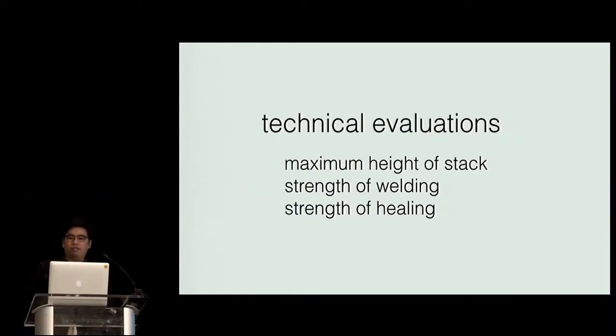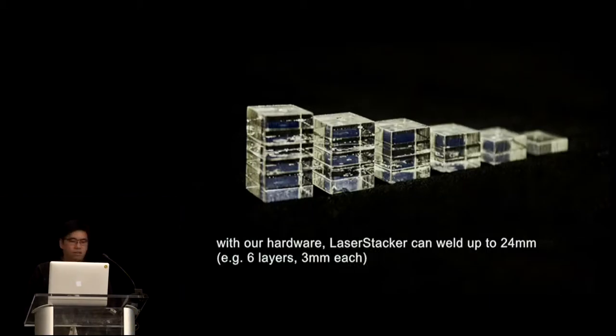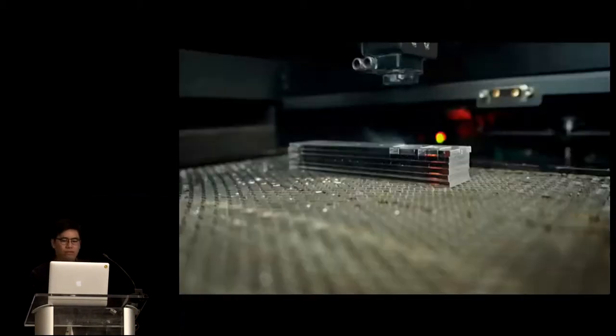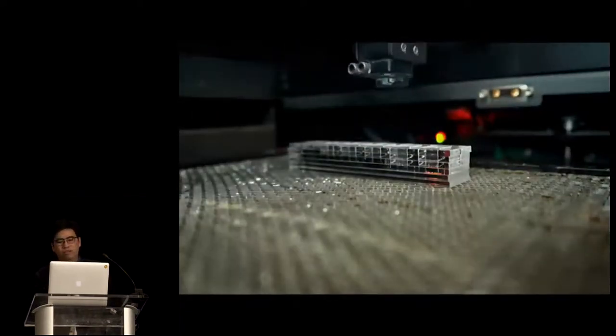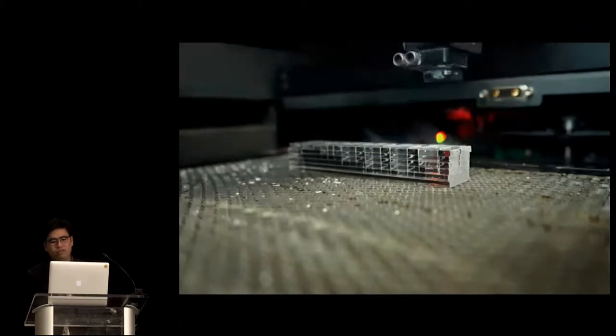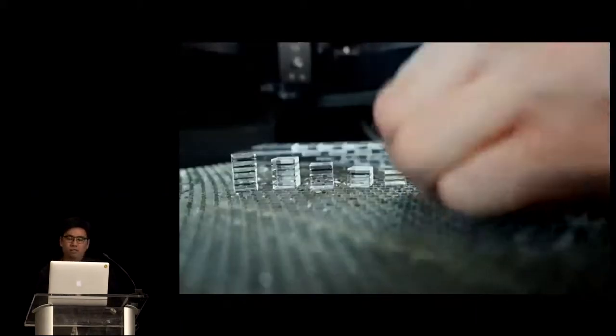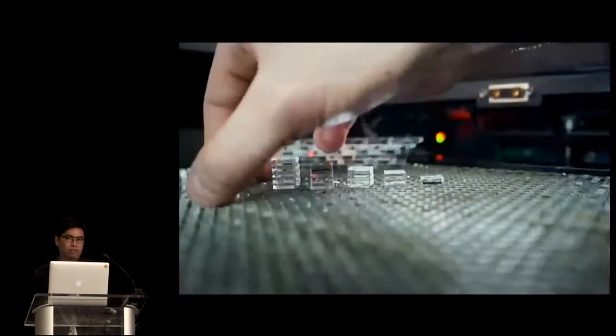All right. Finally. So, we also did some simple technical evaluation. To evaluate the maximum height of stack, strength of welding, and strength of healing. With our hardware, laser stacker can weld up to 24 millimeters. And usually, when it goes beyond 24 millimeters, the accumulated heat in the stack will result in some undesired bubbles next to the cuts.